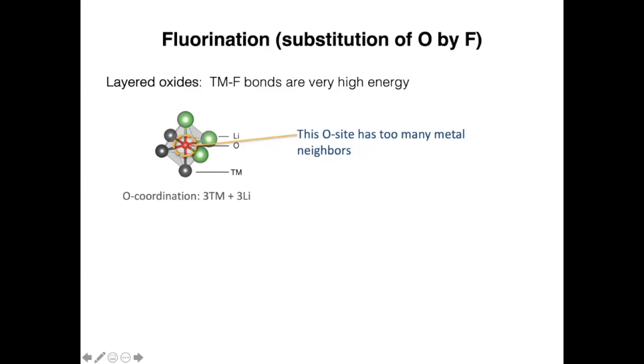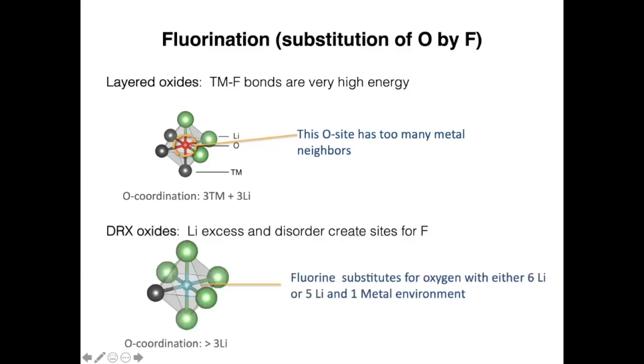If you look at a layered material, if you look at the anion environment, there are three metals. This is the metal layer, and three lithiums. This is the lithium layer. And this anion site has too many metal neighbors to be substituted by fluorine. The energy is way too high. And that's why, you know, people have tried very hard. It's very hard to bring fluorine into a layered material. But if you make a DRX oxide, because you have, first of all, lithium excess, and then you have statistical disorder, you create all kinds of environments, there are certain environments where the anion is coordinated by a lot of lithium, maybe 4, maybe 5, maybe even 6 lithiums, and there fluorine can substitute. And we now know from NMR that it is exactly these environments in which fluorine substitutes.